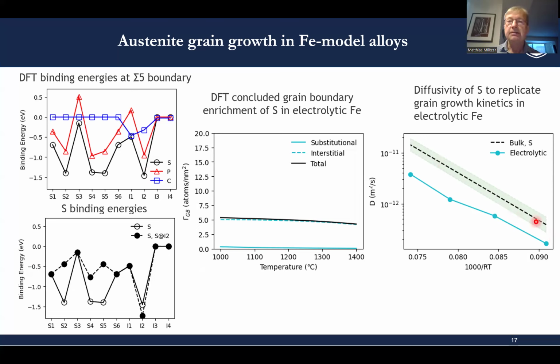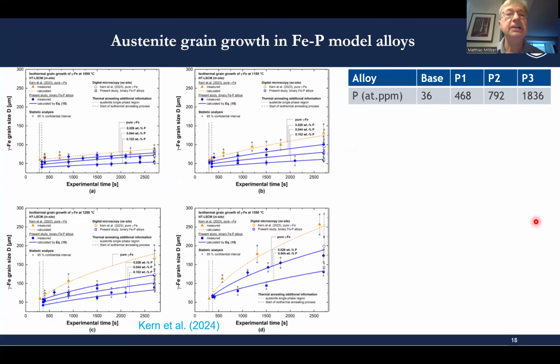And then Kern and co-workers recently engaged in a study where they put phosphorus into their model alloys, and this was recently published. They increased the phosphorus level from the 36 ppm material, the electrolytic iron, to almost 1000 ppm, and they found what was expected. Adding phosphorus would delay grain growth, reduce the grain growth rates, and we can do a very similar solute drag analysis here. Now it's the competition between sulfur and phosphorus for segregation.